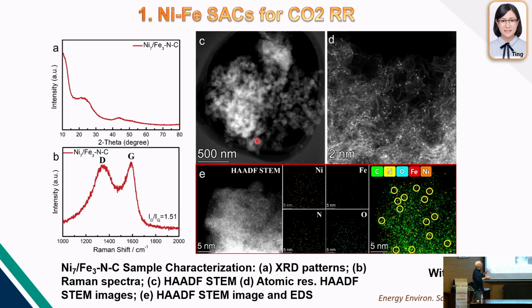So you see, in electron microscopy, we see here the kind of graphitic structure, with all the planes that look like graphite. But then we are at 2 nanometer scale, and every one of these single bright spots is a single atom. And this has to be, for sure, a metal, because the metal has a high Z number, high atomic number, so it's really bright compared to the carbon, nitrogen, and oxygen.